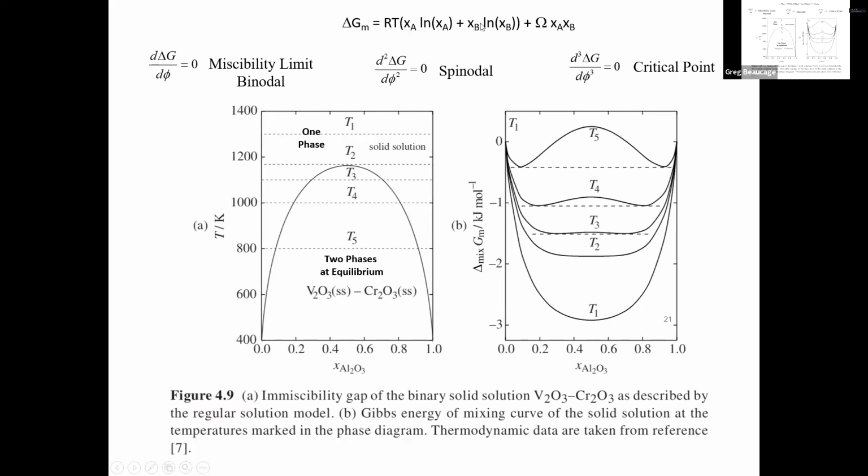Also, this is mole fraction. There's a couple of differences with Flory-Huggins. Flory-Huggins uses volume fraction, divided by the molecular weight, so you're counting molecules. Again, entropy depends on the number of things, so it doesn't depend on how big the things are. If you're mixing polymers, there's a lot fewer things because they're glued together into a chain.